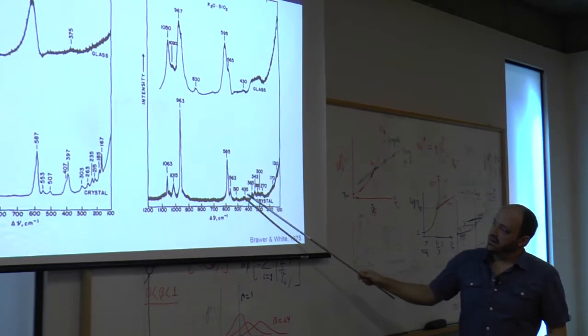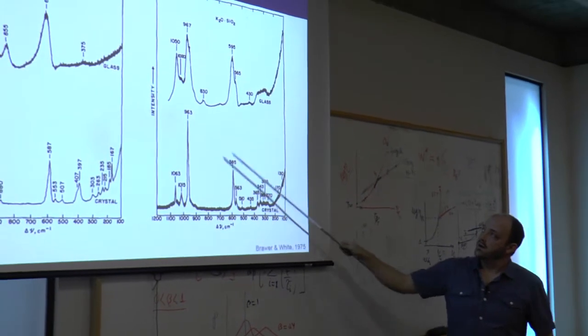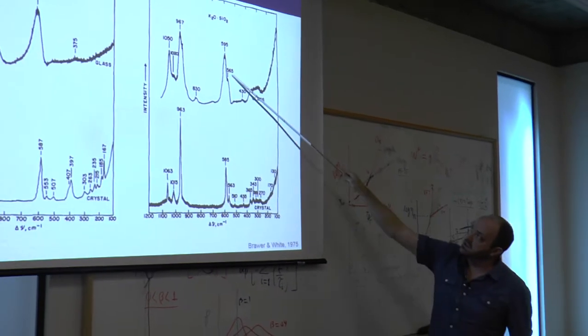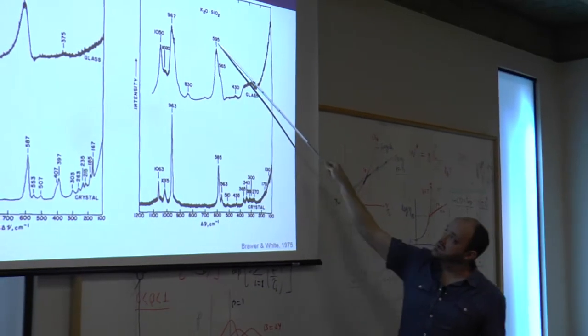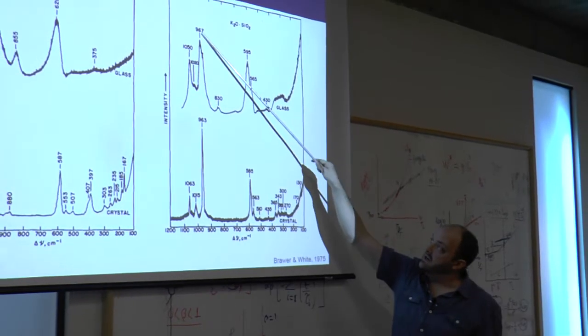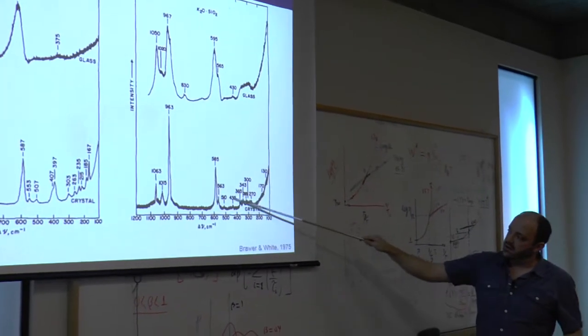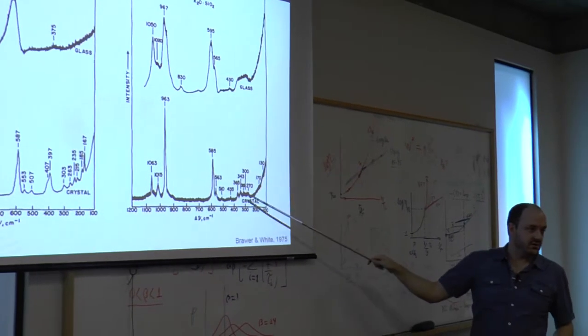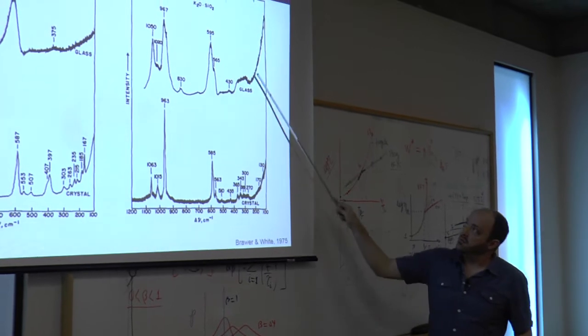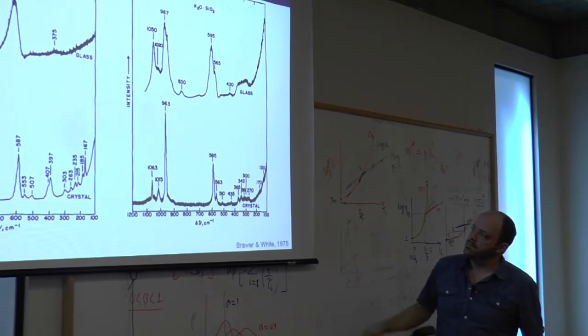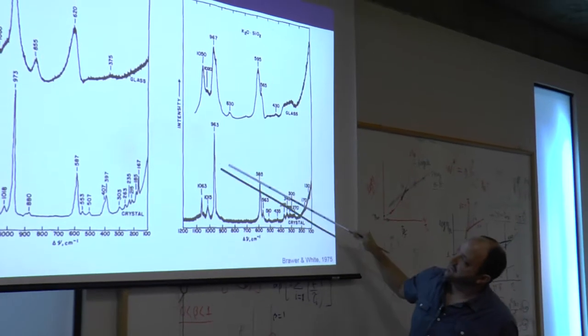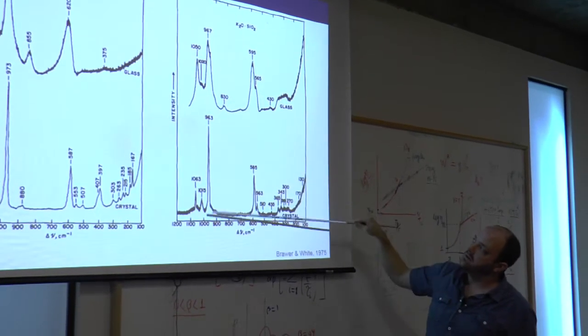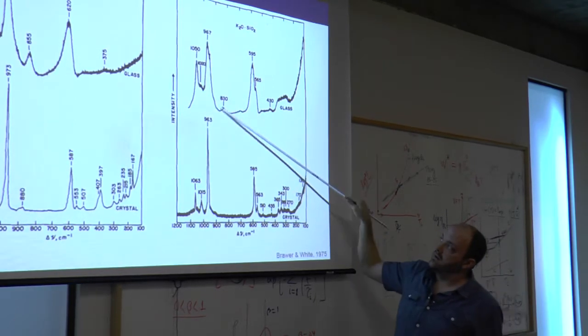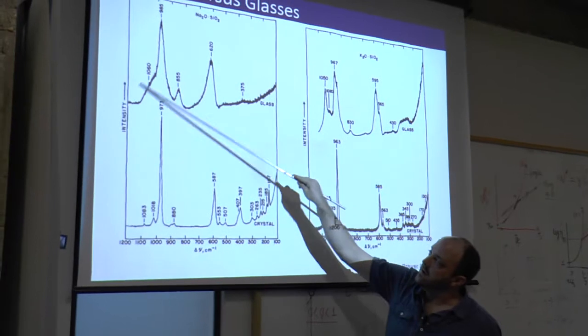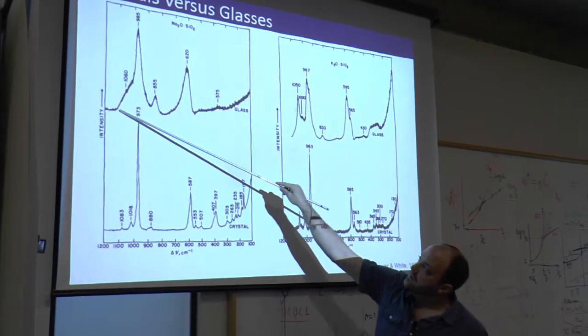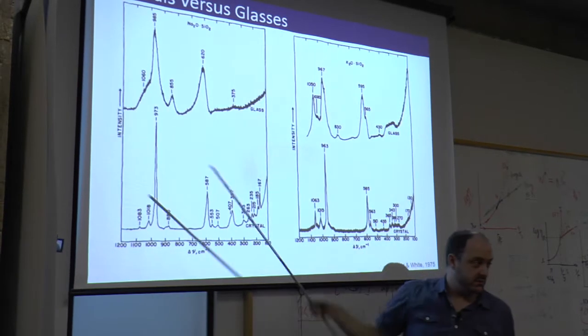So the main features of any crystal, these very strong bands, appear to be the same as the glass. The positions are very similar. You see 585 versus 595, 963 versus 967. And there's lots of other bands in here. These are lattice modes of the crystal, which we don't actually see in the glass. But we have some other vibrations in this region as well. And the key feature that they observed is that for this high frequency band, this is where those QN antisymmetric stretching vibrations are, they get a lot of other vibrations. You see a big shoulder here that's quite wide. This is over 100 wave numbers here.